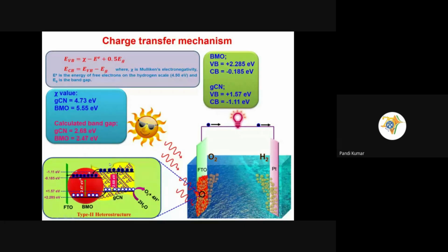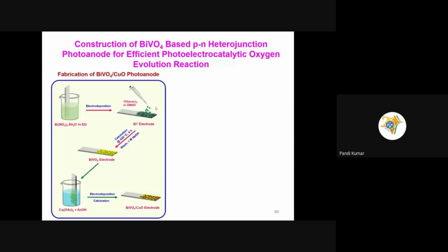In this particular work, the materials we prepared as a powder, then we fabricated the electrode. Finally, we carried out all the experiments. So that's why we got the poor performance of this material. Then we shifted to the thin film based method. In this case, we form the heterojunction between the bismuth vanadate and the copper oxide. The bismuth vanadate electrode is fabricated by electrodeposition, and forming the heterojunction is also carried out by electrodeposition with copper acetate and acetic acid.